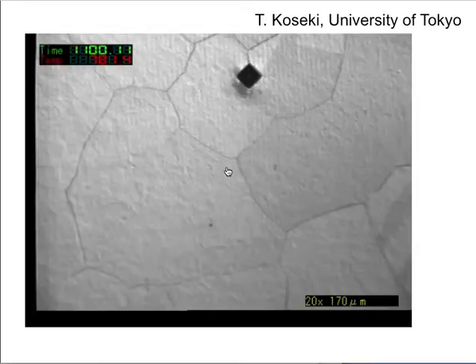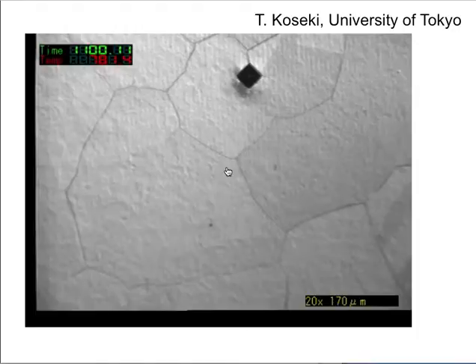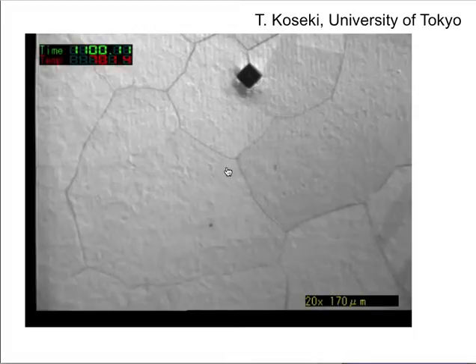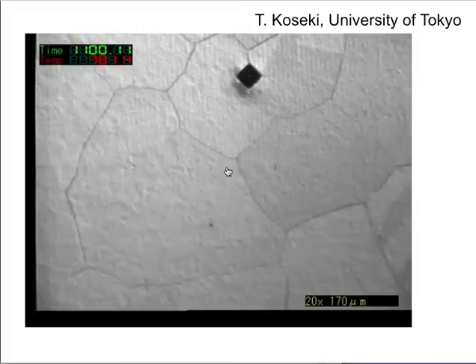This is going to be an extremely boring movie to watch, but it is worth watching just to show that there is nothing happening. The red indicates the temperature - it is about 780 at this moment and by about 720 the transformation to ferrite is completed. Because there is no surface relief and we are not etching the sample, you may not actually be able to see anything but the very faint features when the ferrite forms.